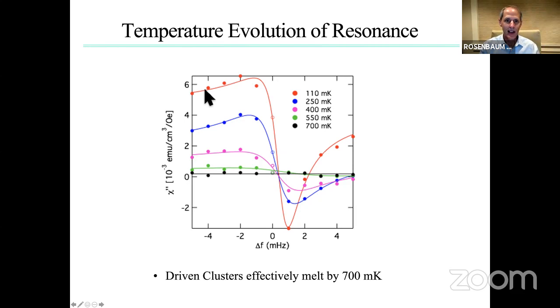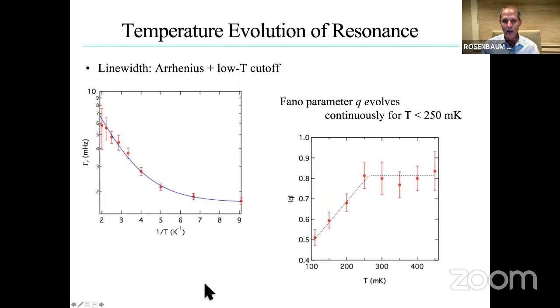Okay, so here, at low temperature, 110 millikelvin, is the imaginary part of the susceptibility versus delta F, which is the difference in frequency between the drive frequency that's exciting them and the one we're looking at. And you see here, you get a nice Fano line shape. As I increase the temperature, and this goes up to 700 millikelvin, the line shape basically broadens until at the highest temperature, I've effectively melted the clusters. So I've just driven them apart. Their binding energy is such that they're not going to be able to sustain those high temperatures.